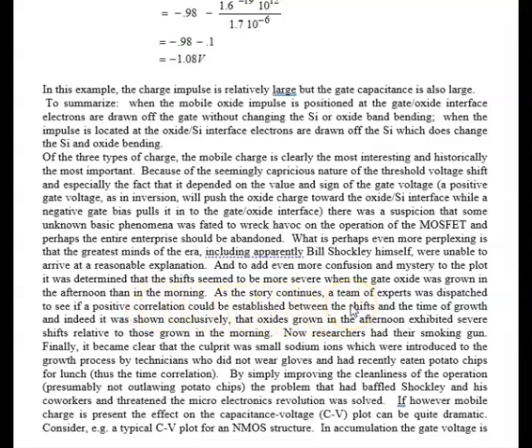Well, anyway, as the story continues, a team of experts was gathered together, and they're trying to figure out what kind of correlation is there between the time of oxide growth and the shifts in the CV plots on the poor yields. And it was shown conclusively that oxides grown in the afternoon exhibited the most severe shifts and the most deleterious effects in device performance.